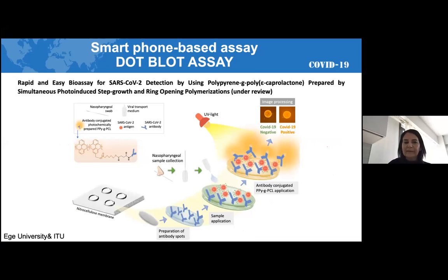A similar system was also fabricated using another fluorescent polymer, a synthetic material, polypyrene grafted polyepsilon caprolactone, prepared by simultaneous photoinduced step growth and ring opening polymerizations and click reactions. This part was performed by Professor Yusuf Yağcı at Istanbul Technical University, and we just functionalized this fluorescent polymer and used it to spot on nitrocellulose membrane to obtain a dot blot assay. We can also obtain these results under UV light. We can see the difference between negative and positive samples, and the color density is related to the virus load.